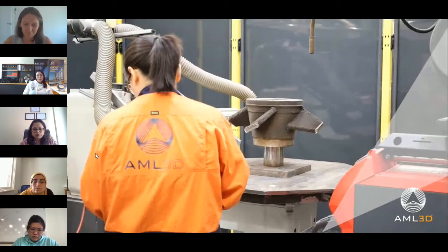So by the time you do the maths, you're looking at a 95% material waste saving, and you're also looking at a considerably lower build time. So to machine a 460 kilo billet to a 22 kilo part, you're looking at 97 hours of machine time alone. For us, in our wire additive manufacturing process, you're looking at 23 hours of arc and machine time in total. So it's considerably less.